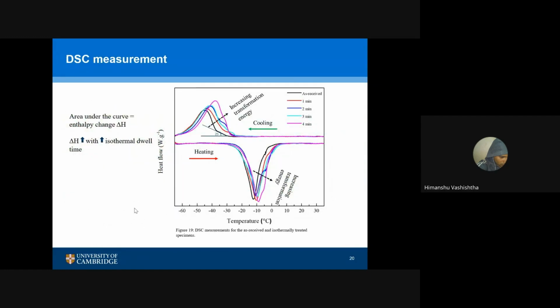Now, a pretty good thing, the DSC measurement, differential scanning calorimetry. We have gone through very detailed calculation for these heat treated specimens. For the as-received sample, a black line is there, and you can see an abrupt change around 25 degrees.